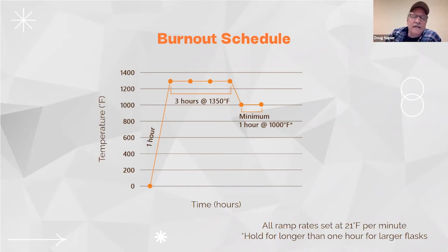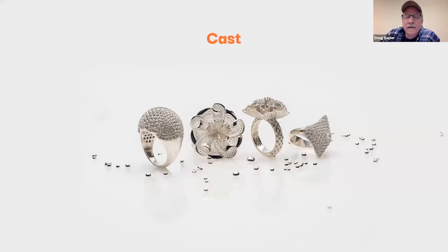To me, the reason I did it is because I know that between 700 and 900 degrees, that resin is starting to react. And I just figured, I'm just going to blow by that as quick as possible and let it do its thing, and then get it up to temperature so that it burns out quick. And again, for the most part, this is my burnout schedule. If I'm burning out overnight, I'll use the longer one, but usually I'll come in the morning, tree up and invest, and usually I'm cast by 1 o'clock or so, and then I can clean up the piece and get it going.